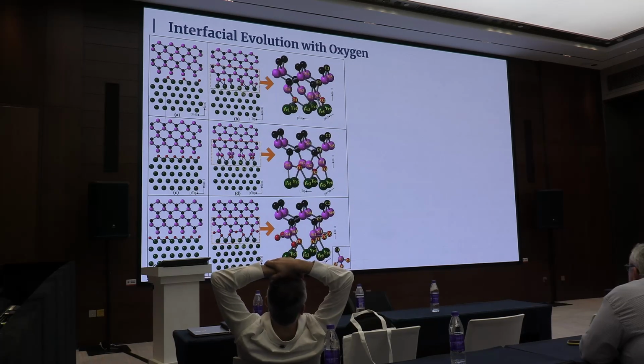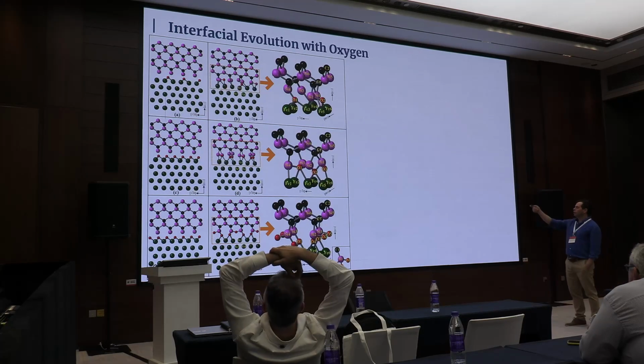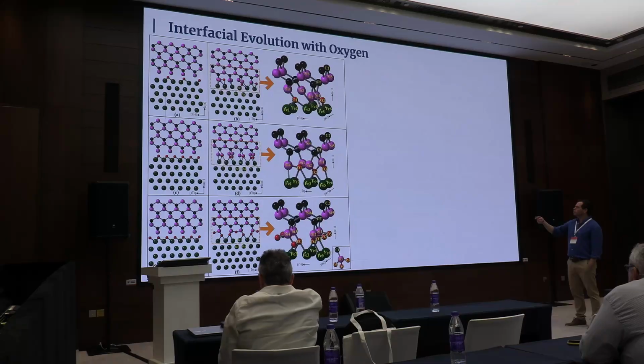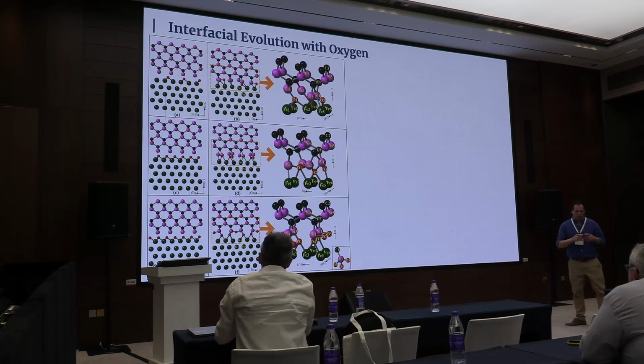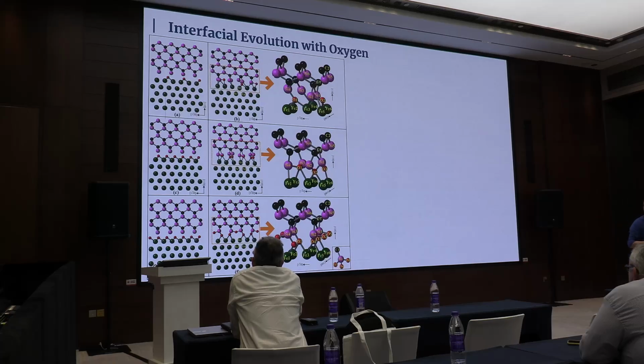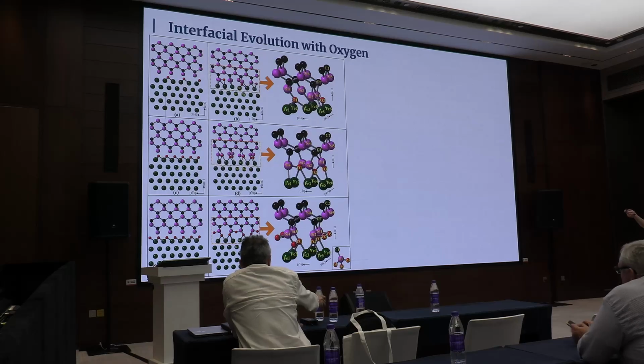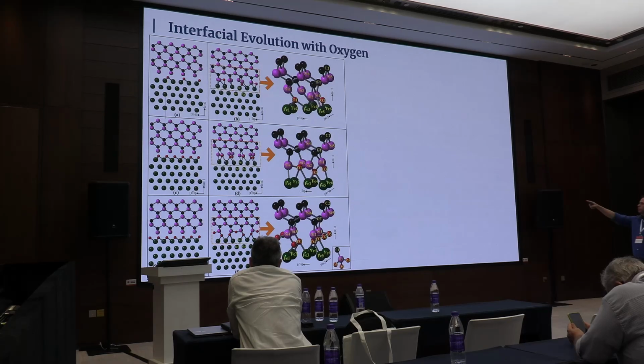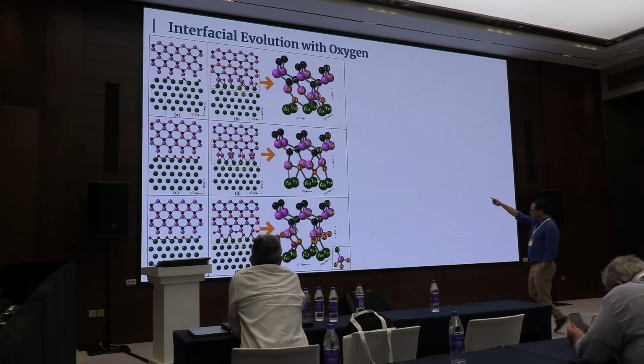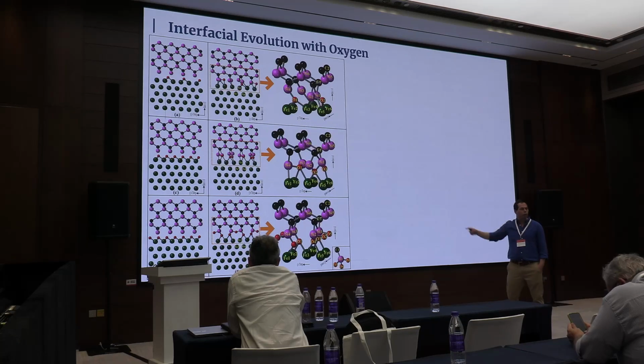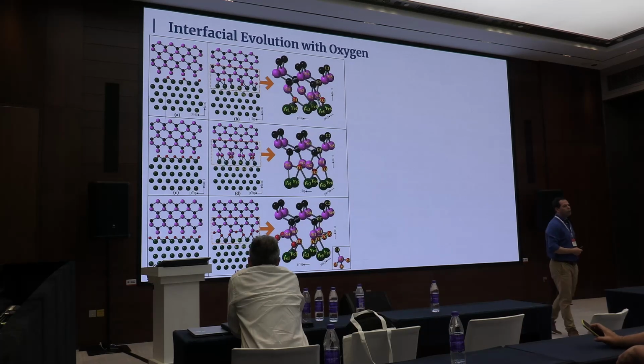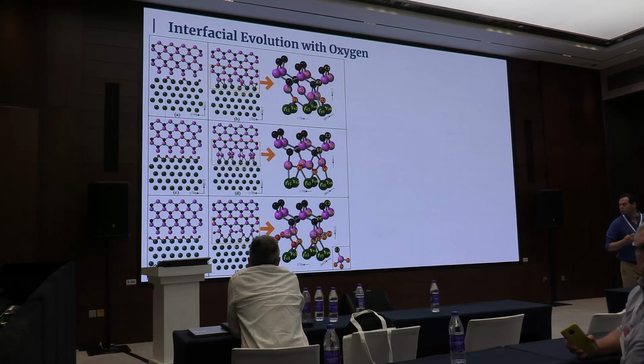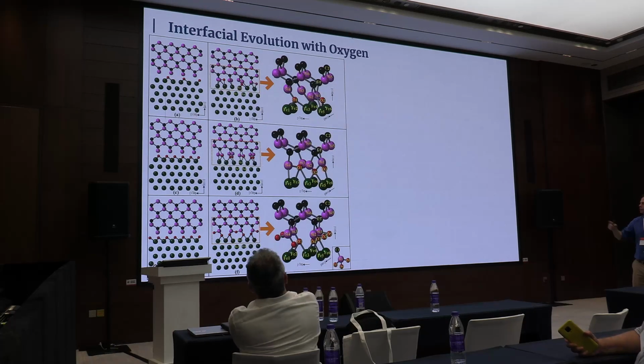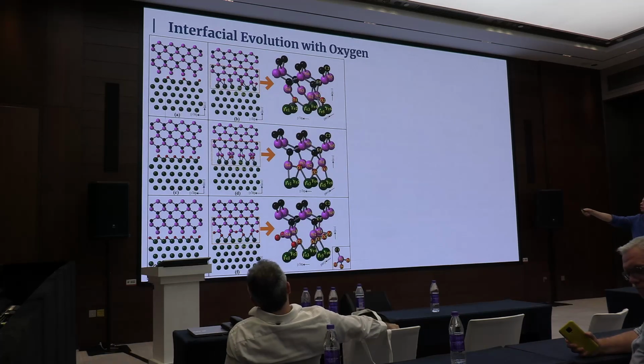And if we zoom in on the interface, we observe a change in the distances of the atoms, and the oxygen's preference for silicon atoms over the iron. But the most important thing to observe here is that as soon as we increase the amount of oxygen we are adding, we are changing a bridge. We are changing the bond between silicon and iron.